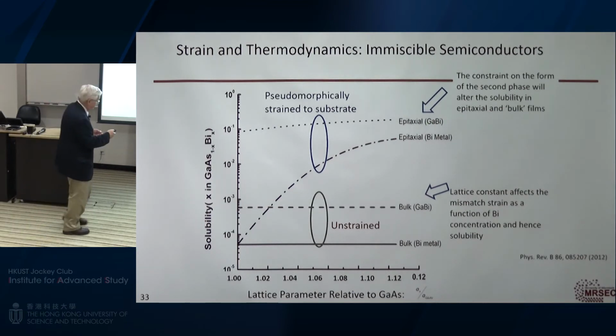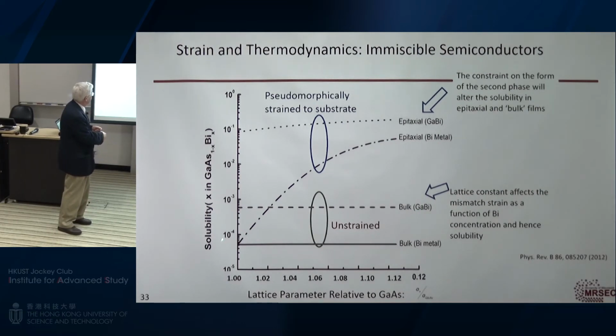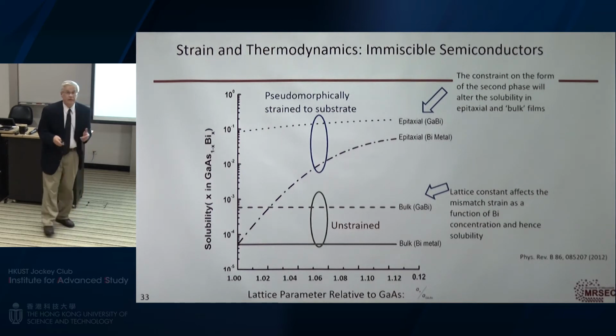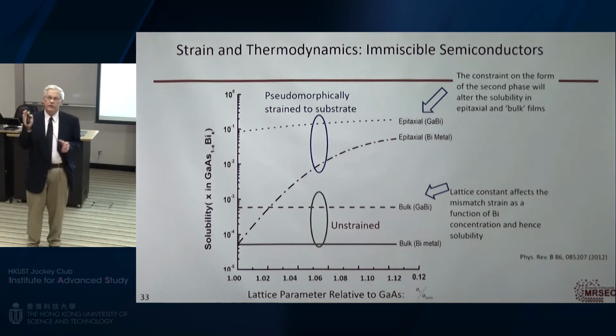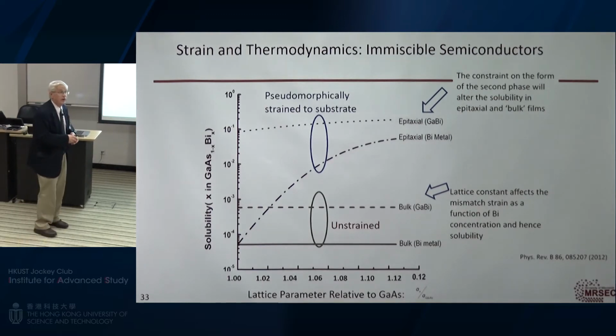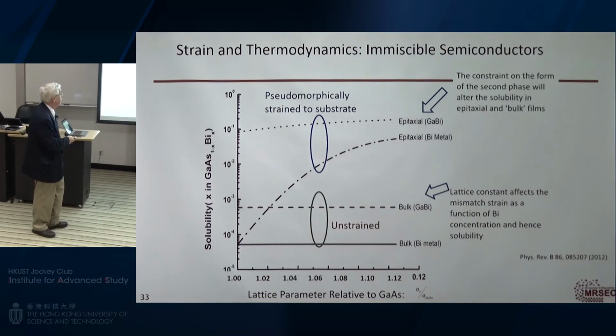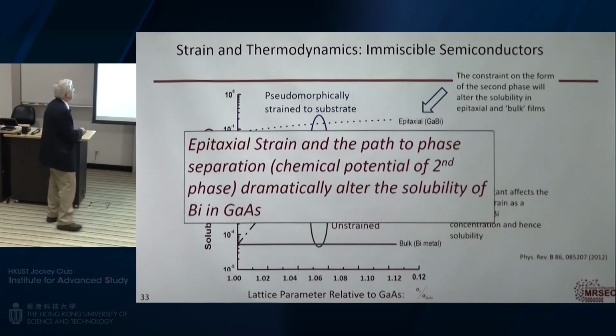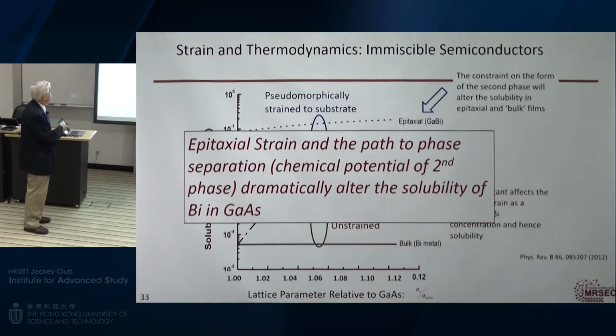So if I look at gallium arsenide bismuth by itself, I can get very little bismuth into the system. If I get about 10% bismuth into gallium arsenide, I can make a laser that probably has no, for those who work on lasers, Auger recombination, meaning it would be very, very efficient lasers. And that's because of the band structure, which we can compute. And this thermodynamics was computed using DFT. So epitaxial strain and how it decomposes can dramatically alter the solubility.